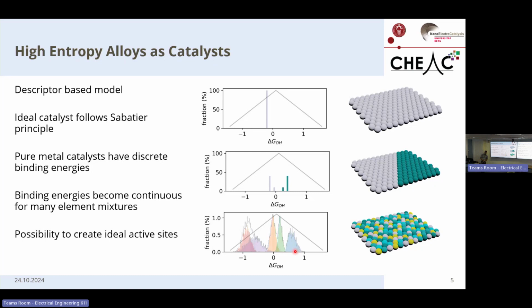One of the main properties of high entropy alloys is very low diffusivity, so a low diffusion coefficient. Does it affect the activity of the catalysts? Diffusion within the solid, I mean, on the surface as well, because it causes more lattice distortion. I'm not sure if the surface is affected by the sluggish diffusion, because the surface elements are uncoordinated, so they are generally more mobile. But I thought it's because we have more different elements that cause lattice distortion.